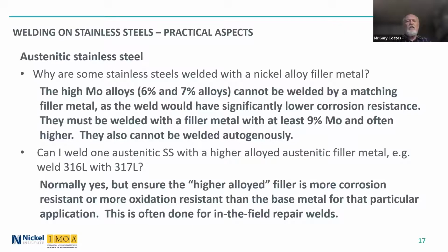And the technique of using a slightly higher alloyed filler metal is fairly common when doing in-the-field repair welds. In field repair welds, you can't get the same level of cleanliness, and the external environment isn't all that clean. It might be hot and humid, and so it helps to make the weld metal a little more corrosion resistant. There are a number of chemical companies and pharmaceutical companies that will do this.